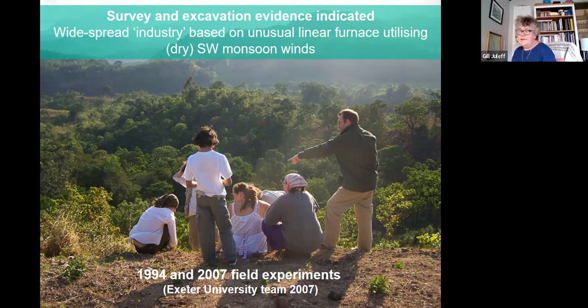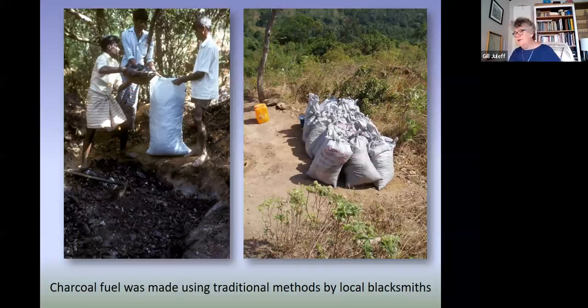So really, on the basis of that, we concluded that the only way that we could take the research further was to actually reconstruct a furnace during the monsoon to see what actually happened, and if it could reach the temperatures that we needed it to reach to be able to smelt iron, and how it functioned, which is what we set out to do initially in 1994 and then again in 2007. And so the next set of slides come from the various different experimental smelts that we've undertaken, and they're just to give you an overview of that process.